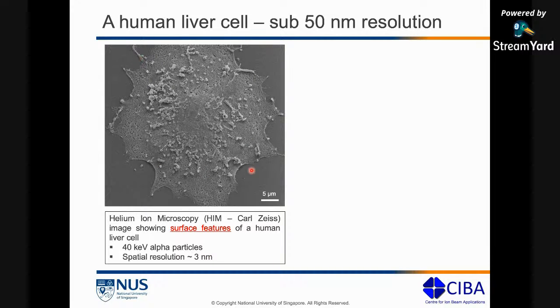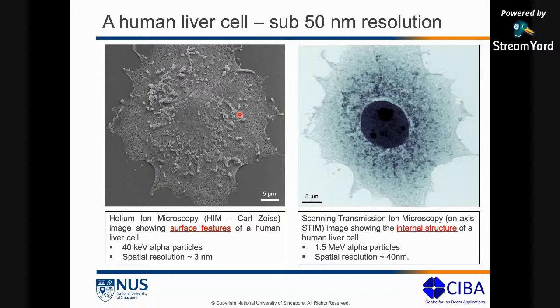We took the same image in a helium STIM setup, and this is what we got. What we now see in a helium STIM image is that the spatial resolution has slightly dropped. Now it's about 40 nanometers. But what we are able to get from a helium STIM image is the internal structure of the cell. We are able to see the cell nucleus.